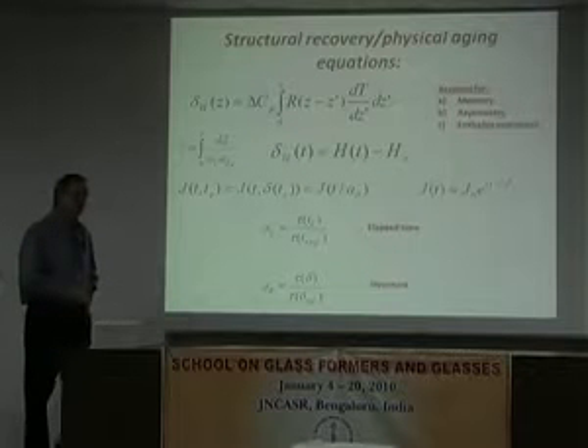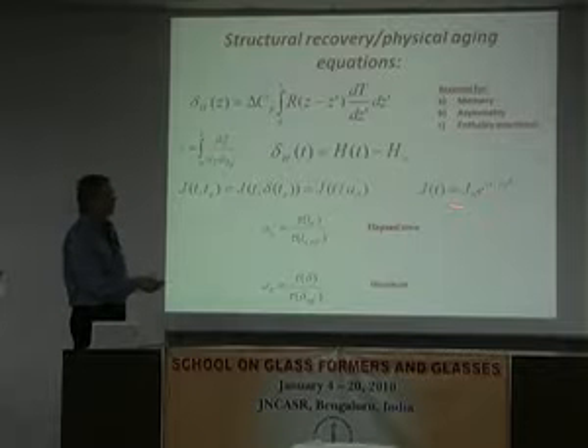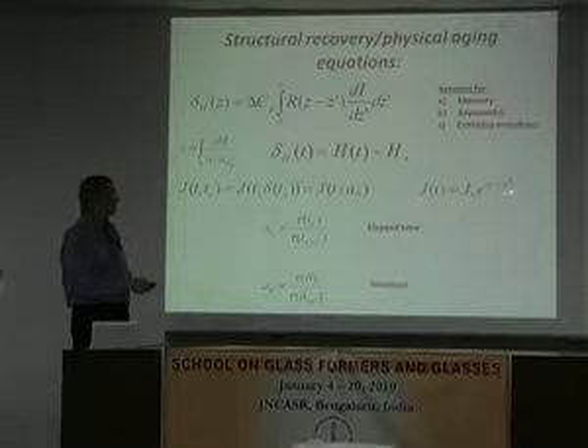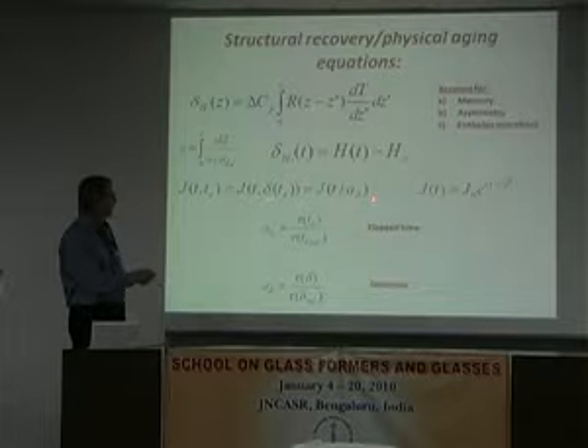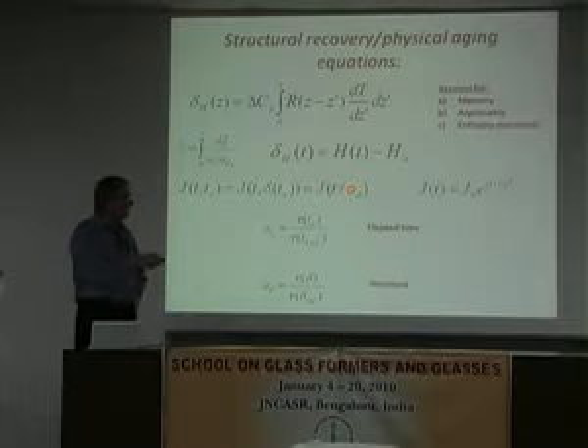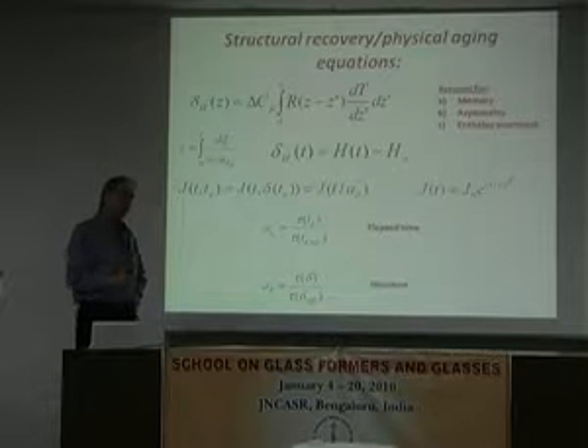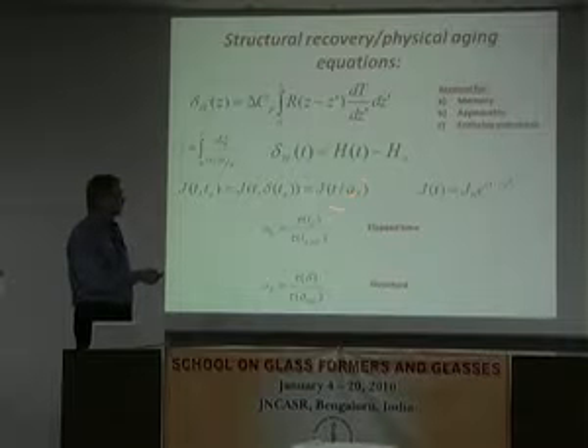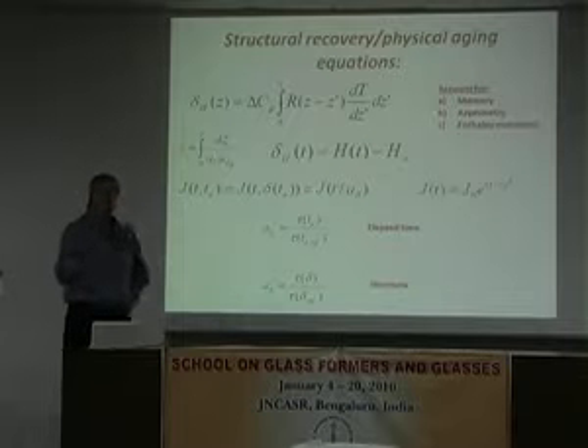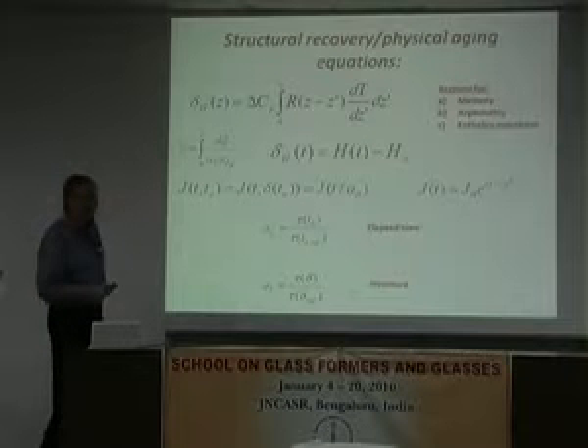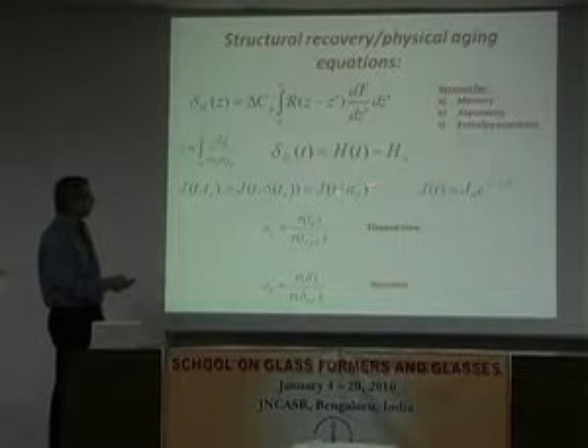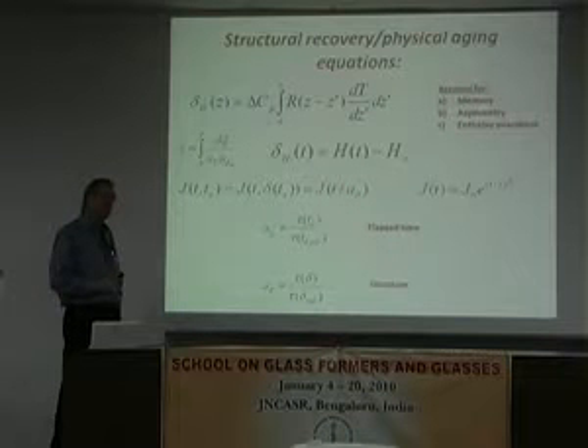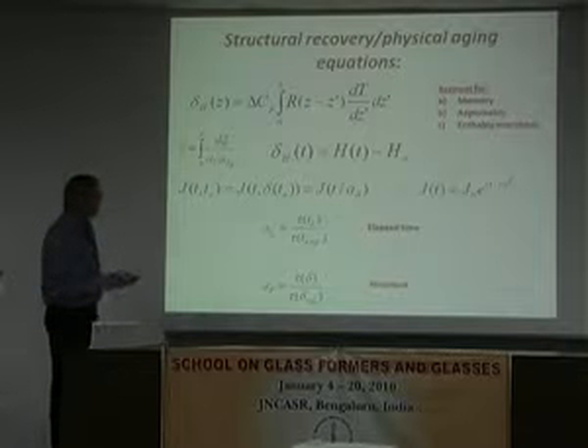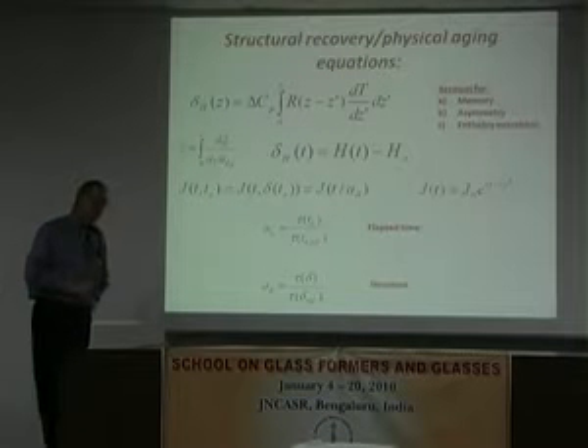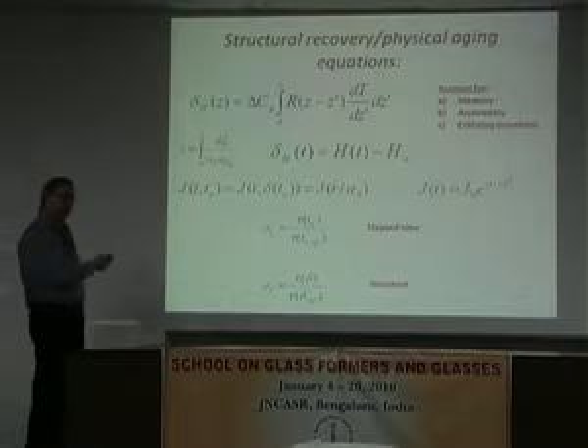Where is what coming from? This is just an assumption. This is how you write time-temperature or time-aging time superposition. So this is a reduced time idea in viscoelasticity. If I had time-temperature superposition, I would just put an a_T in there instead of an a_delta. And that's how the linear viscoelasticity community would write this equation.